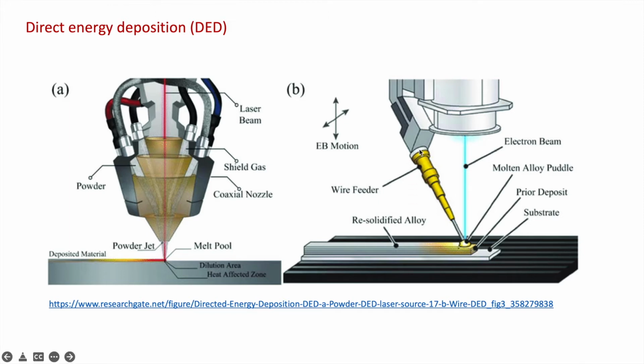In this approach, a wire is fed to the printed component. Either electron beam or high energy laser will melt the wire, and after solidification, this process continues in a layer by layer fashion. Just now, we have mentioned the major advantage of using DED compared to the laser powder bed fusion. Then what is the major disadvantage of using DED? The main drawback of DED is poor spatial resolution.